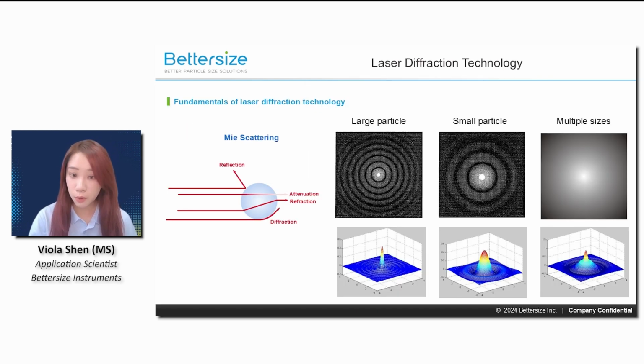So let's start with the principle behind laser diffraction technology, which can be used to find out the particle size of the additive manufacturing materials. As the figure depicted on the left, when light shines on a particle, light scattering occurs as a combination of four phenomena: reflection, attenuation, refraction, and diffraction. The diffracted light projects a pattern on the screen, forming a series of concentric circles of varying intensity, known as the Airy pattern. With a fixed wavelength and distance, these patterns change systematically with particle size, as the figure in the middle shows for large particles and small particles. In practice, particles of different sizes produce a combined diffraction pattern or spectrum, allowing comprehensive particle size distribution analysis. This makes laser diffraction an essential tool across diverse applications.